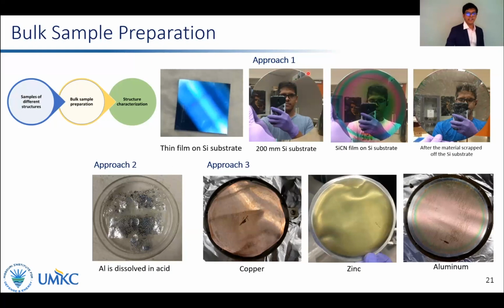The first approach included depositing thin film on a large surface area silicon wafer and scraping the film off the silicon after deposition. This worked well for samples deposited at low temperatures, but at elevated temperatures the films were very adhesive and hard, and we couldn't scrape them off the silicon wafers.